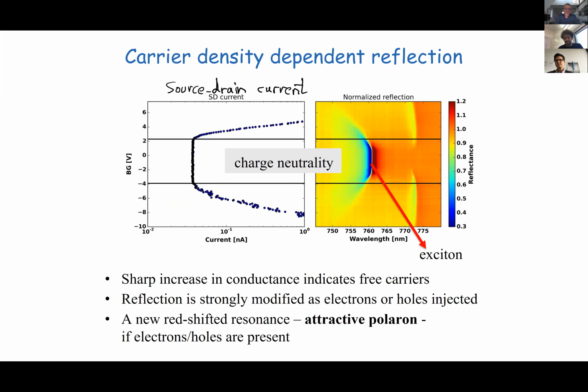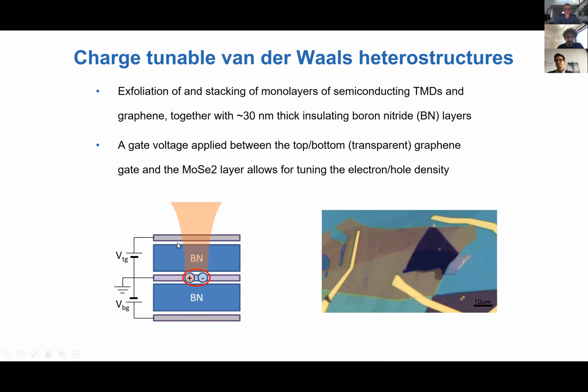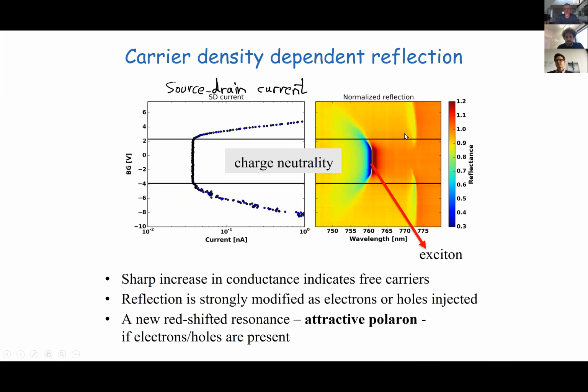Okay, so now what happens to this system? Basically, the applied voltages allow us to control the charging. And if the TMD is neutral, that is, devoid of free electrons and holes, we see the exciton resonance. This is the color-coded plot, which shows how much the reflectance contrast changes. And you can see that this really is of order unity because of this mirror effect that I've told you about.